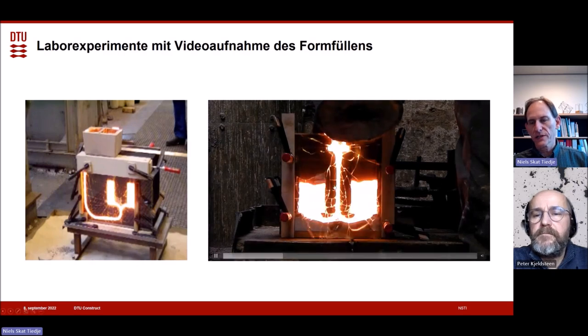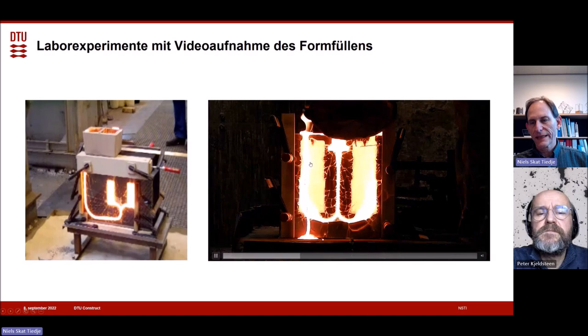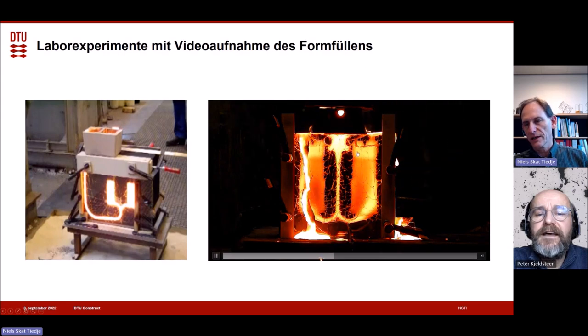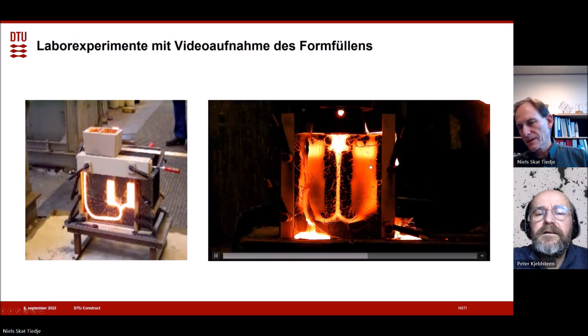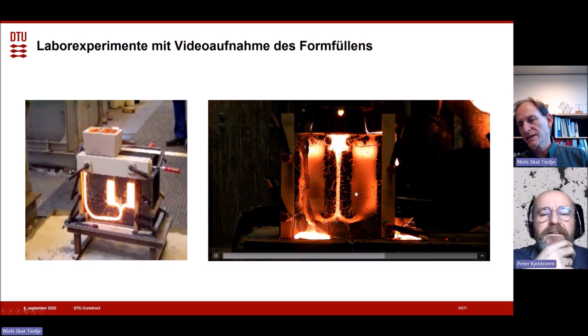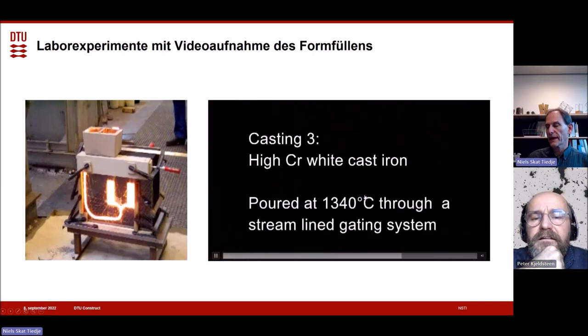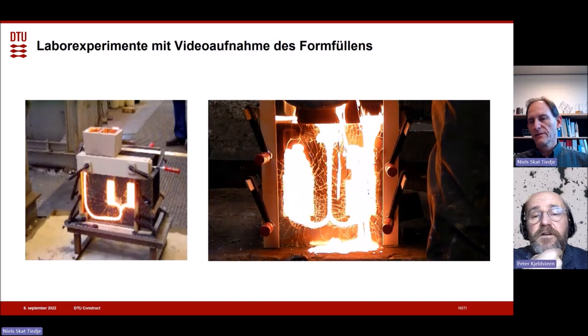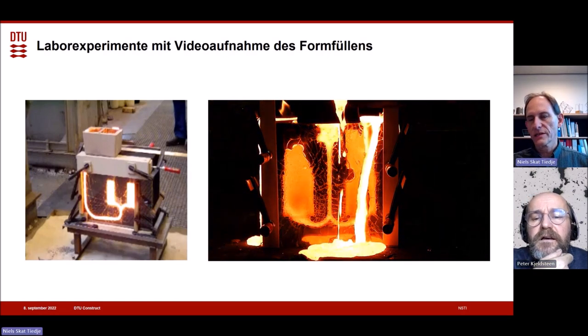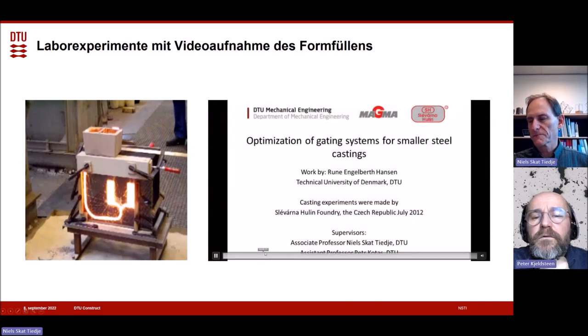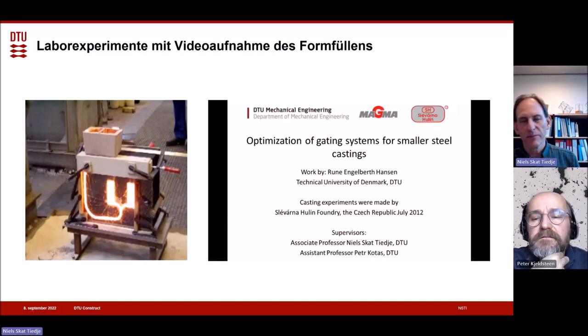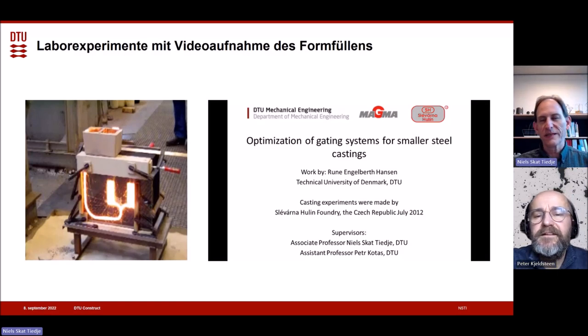In this case, at 1420 degrees, we can see the melt is hot. It feels really nice. If we wait a little bit and pour at a lower temperature, you can see the temperature gradients here quite nicely. Here's a feeder, high temperature, retains the heat for a long time. Wow. The flow heats the material here. Here it's cold. So you actually can see the variation in cooling rate and the resulting variation in mechanical properties in the material. Here we are at a lower temperature, 100 degrees lower. Yeah. 80 degrees, and you can see the material solidifies before it fills. It solidifies too early. So we see some very cool stuff just by making videos. This is old. You can do much better things today with videos.